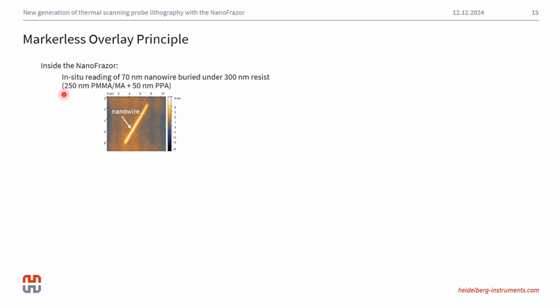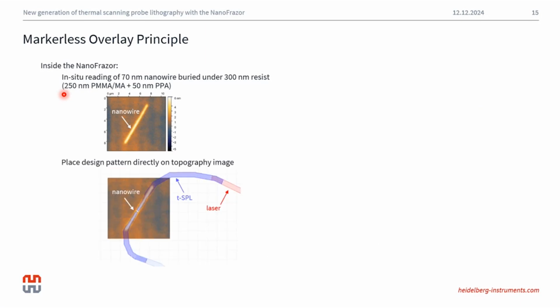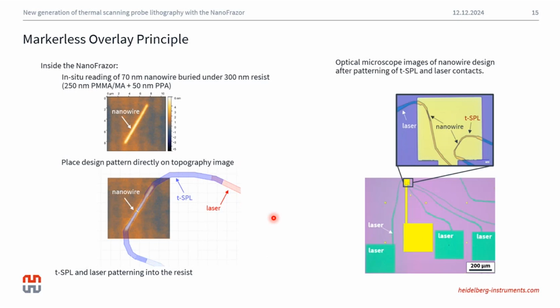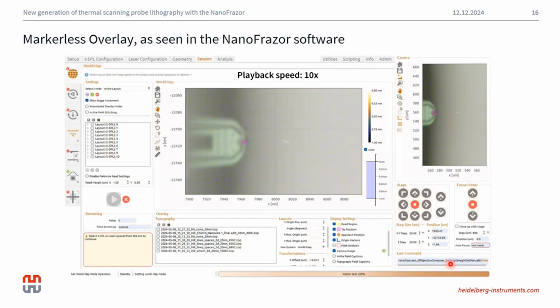Once we have the NanoFrazor topography image, the target pattern to be written can be directly dragged on top of the nanowire, and the patterning can be launched. In this example, you can see how we use a combination of thermal scanning probe lithography, or TSPL, to create the fine contacts, and then we can use the laser writing to create the electrode fan-outs and larger structures. This is an optical microscope image of the resulting device, and I'll show you here how this was done with the NanoFrazor. This is a screenshot of the NanoFrazor interface, and I'll launch this video.